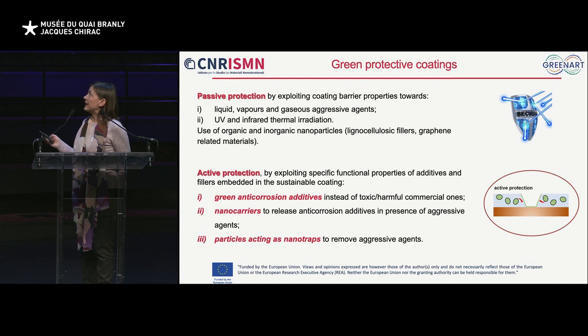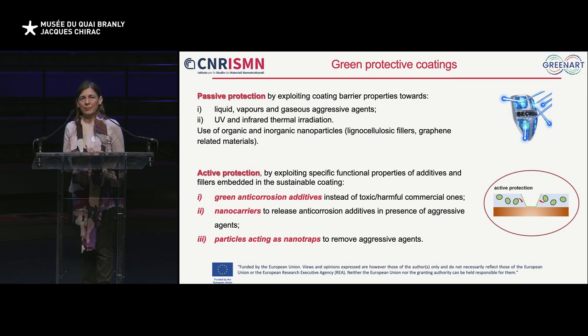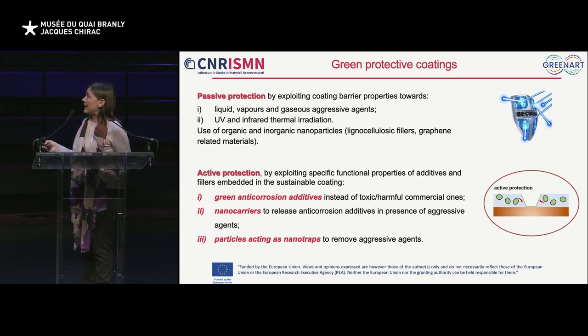So in parallel, within the GREENART project, we are working on 2 different aspects. One aspect is the passive protection. So we introduced into the biopolymer coating fillers which can improve the barrier properties, thus avoiding, for example, the permeation of atmospheric degrading agents, and so increasing the protective action. In parallel, we are working on the active protection, in particular on the identification of green anti-corrosion additives to replace the benzotriazole, and on a nanocarrier which can release in a tailored way the protective species and reduce also the diffusion of degrading agents.